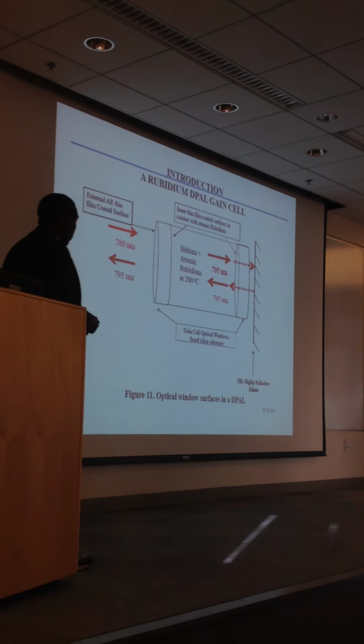So taking a closer look at the laser, I guess you've seen this before in kind of a summary, but what's different here is that we show where we will apply the thin film. So we apply an anti-reflective film in front of the 780 nanometer beam, usually a quarter wavelength of, could be magnesium fluoride. In this case, because of the high power laser, you may want to use something different. So we have an inner thin film coating here, which should survive contact with the atomic rubidium.